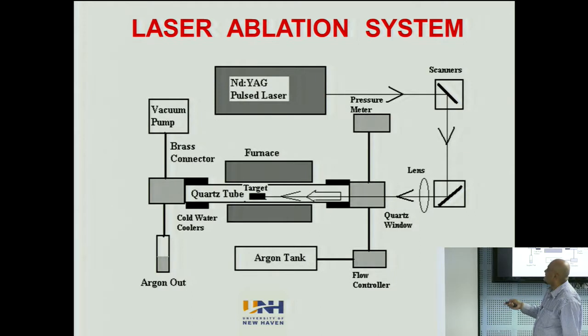So, this is the laser ablation setup that we use for making the carbon nanotubes. For laser ablation we had a target which is the carbon material, and a laser focused on it. So, it makes the vapor form, the vapor goes out and then it gets cooled over here, and these black parts are where the carbon nanotubes form. Now, this target is what? Target is carbon and it has the catalyst material present in it. We used one type of catalyst; depending upon the type of catalyst you get the diameter of the nanotubes that are formed here. In silicon you do exactly the same thing, only your target is now made out of silicon and your temperature and conditions are different.